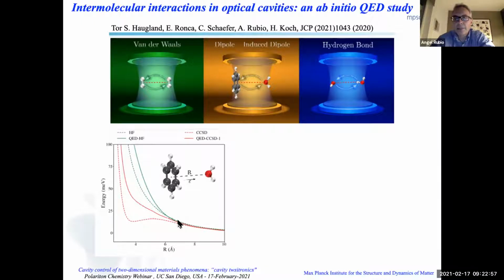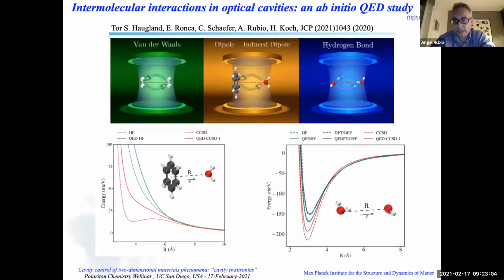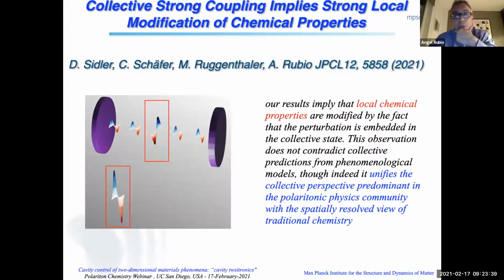Then basically you can control the bonding and anti-bonding nature of the molecule in the cavity by coupling the dipole moment of the complex system to the vacuum fluctuations of the cavity. The same for proton transfer, and this is something which is illustrative of basically the difference between the Hartree-Fock, standard exchange correlation functional in an optimized effective potential, and the coupled cluster. At the end of the day, you see the need of including this type of higher-order correlated methods to describe properly the interaction, but the physics is already captured to a given degree by the functionals that we have in the QEDFT. This was more to illustrate the question of, can you control molecular interactions and can you modify the ground state of a molecular complex in the cavity?